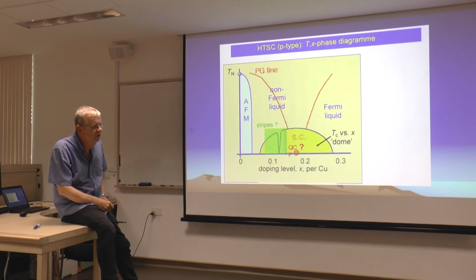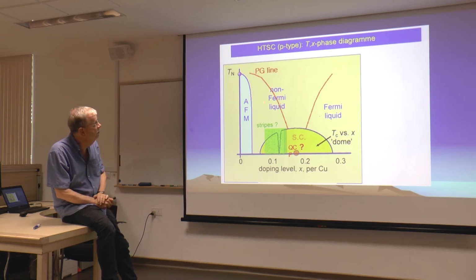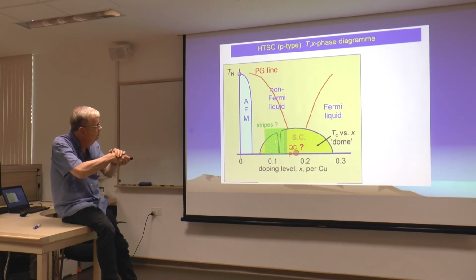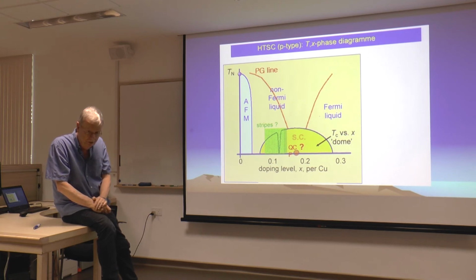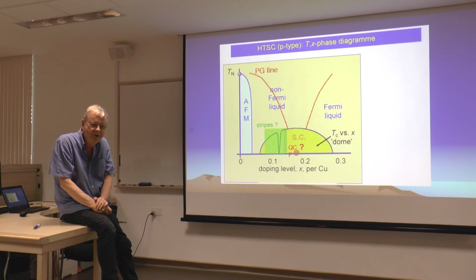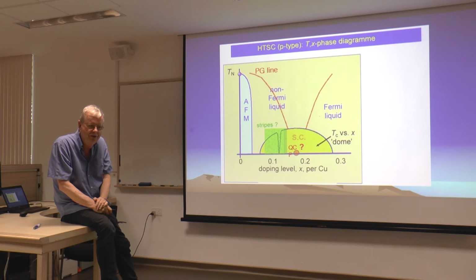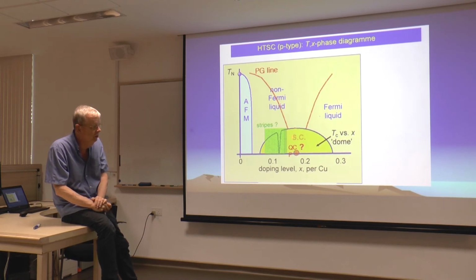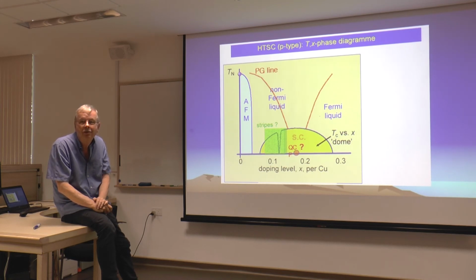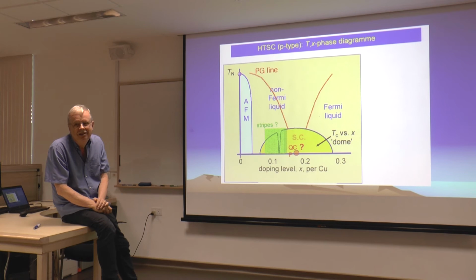the people that study cuprate physics don't understand the superconductivity, so they drew this. I didn't put this here. I put the quantum critical point question mark, but you know, there are iron-based superconductors where antiferromagnetism comes nicely down to the top of the dome, and it's believed there's quantum critical behavior. But the problem is, it's like looking for the lower transition in uranium-thorium-beryllium-13. The fact that you have superconductivity up here buries your ability to measure the resistivity, because it's been shorted. Resistivity is equal to 0, it has no temperature dependence. So if you've got rho goes as T to the first power down here, there's no way to see it until you put a field on to suppress the superconductivity. And if you're talking about YBCO, that's 120 Tesla. Not technically available this week.